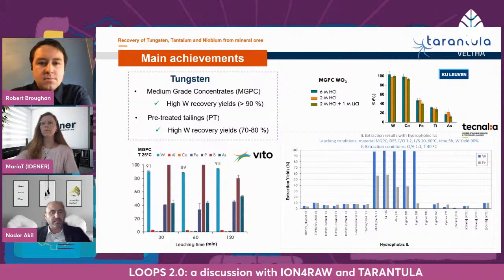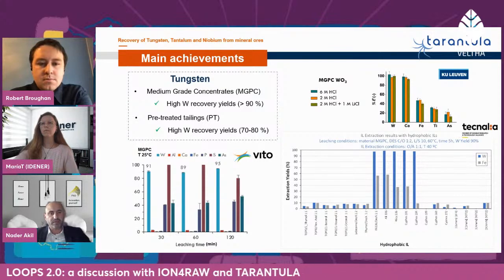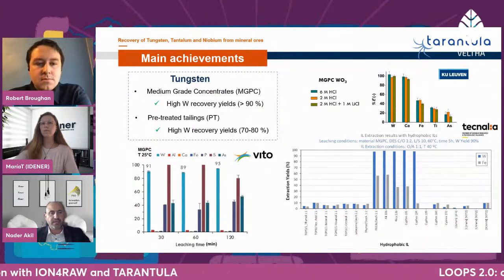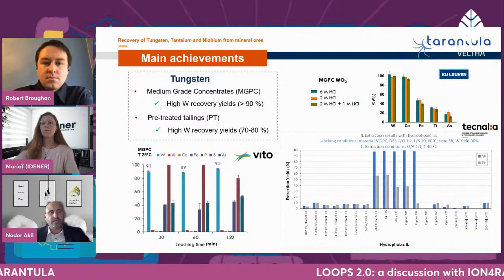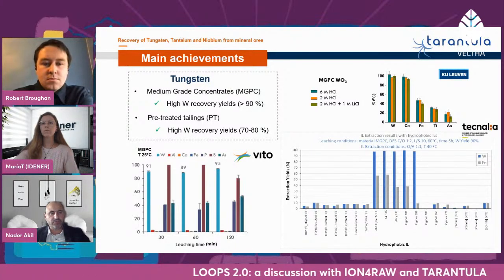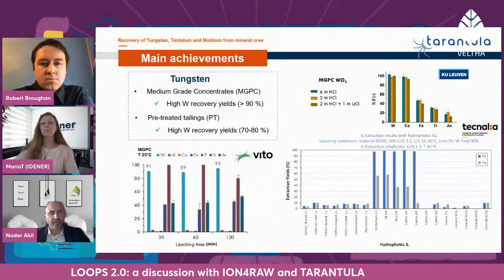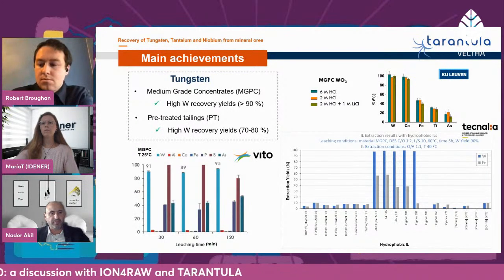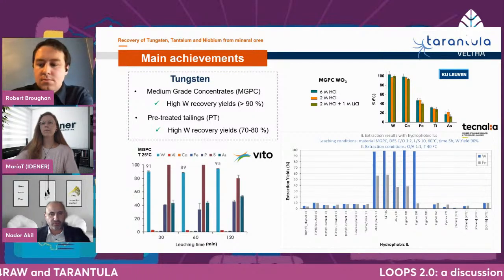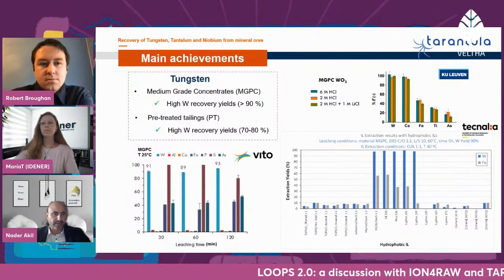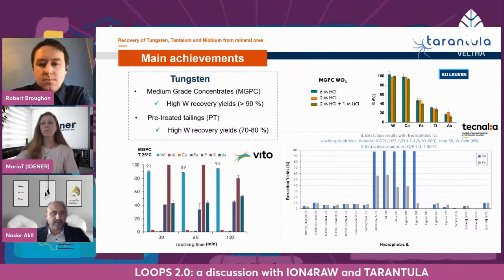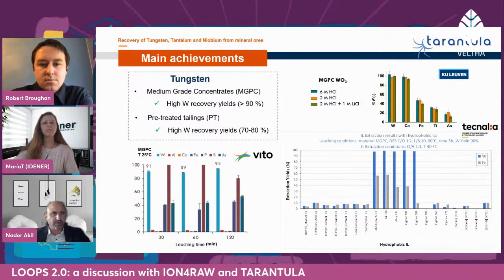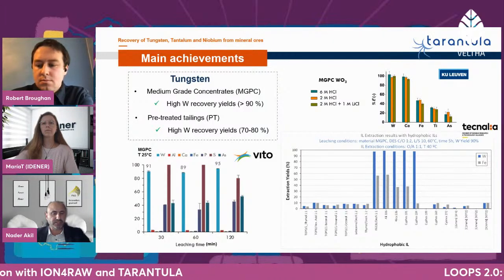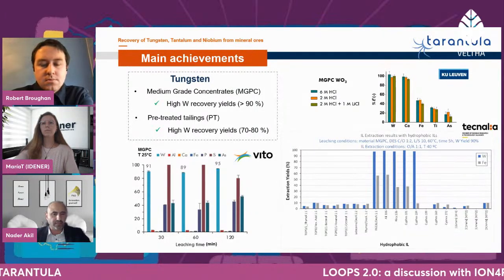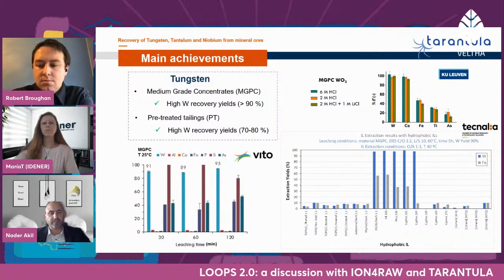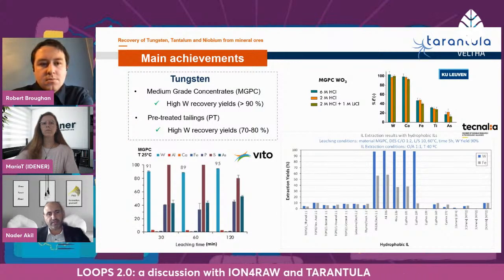This is the achievement so far with the several processes for tungsten, for medium grade concentrates, where we have succeeded to achieve high tungsten recovery yields, more than 90%, as shown in some of those graphs. For instance, here with Vito technology, we can see that the tungsten recovery yield was more than 90%, and the leaching time was between 30 and 120 minutes for performing this operation.